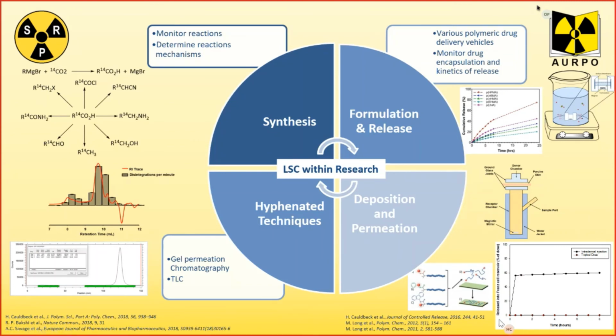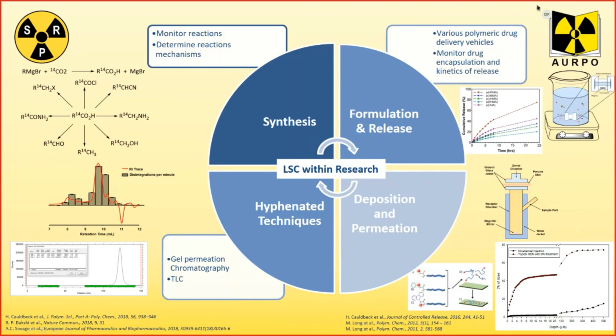So here are some results from using this method, where a topical dose has been applied to the skin and an intradermal injection administered. And as you can see, there is a fast release into the reservoir of the sample injected, and there is no release from the topical dose. At the end of this experiment, we can then section the skin into thin layers and oxidize these thin layers to count those samples to determine the deposition of dose within the skin.